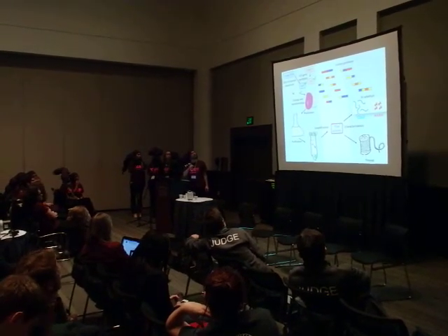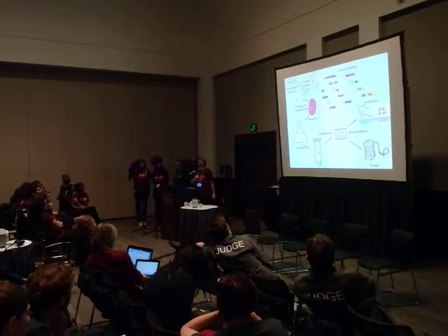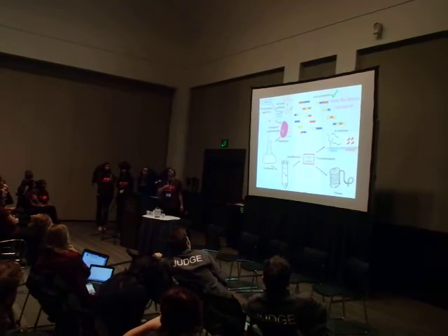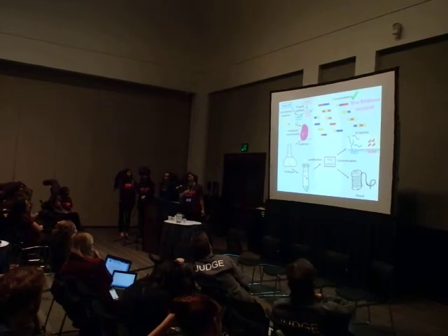That's what we have accomplished. We found consensus sequences for elastin, spider silk, and resilin, and we designed ELP, SLP, and RLP genes. We cloned the ELP gene into E. coli to produce and purify 87 milligrams of pure elastin, and we characterized the fiber by mechanical test. We have also designed fusion proteins and made our new standard to release.